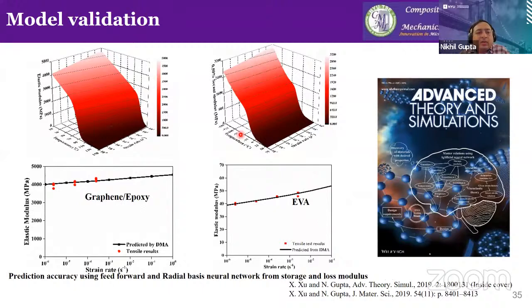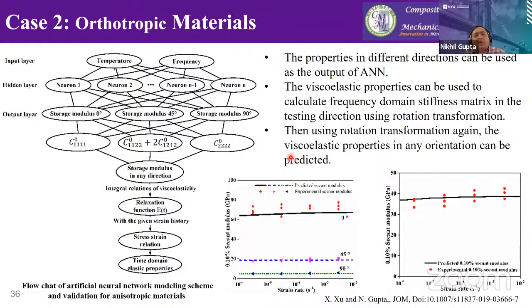And then we tested this for graphene epoxy composites and EVA, apart from many other different polymers that I had shown before. Nanocomposites at the macro scale, you can take as homogeneous materials, and the data matches extremely well for materials like that predicted from the neural networks. This work was featured on the inside cover of Advanced Theory and Simulations. We then conducted experiments on fiber reinforced composites. The architecture again remains the same, but the directionality of fibers becomes one of the considerations here. So one of the layers was related to the storage modulus at 0 degree, 45, or 90 degree, which means different directions of fibers.